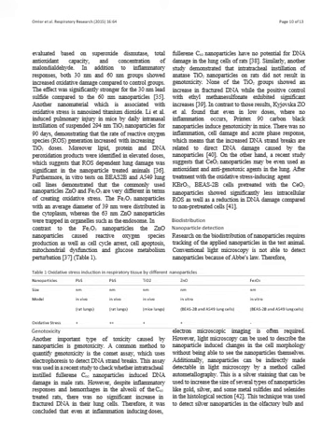On the other hand, a recent study suggests that CeO2 nanoparticles may even be used as antioxidant and anti-genotoxic agents in the lung after treatment with the oxidative stress inducing agent KBrO3. BEAS-2B cells pre-treated with CeO2 nanoparticles showed significantly less intracellular ROS as well as reduction in DNA damage compared to non-pre-treated cells.